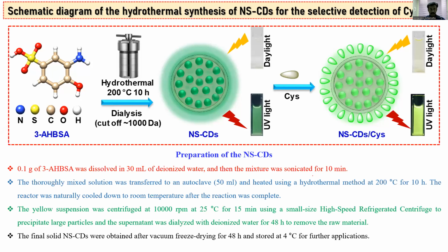Finally, we can get the solid carbon dot material, obtained after vacuum drying for 48 hours. And then we have to store this material at 4 degrees Celsius for further applications.